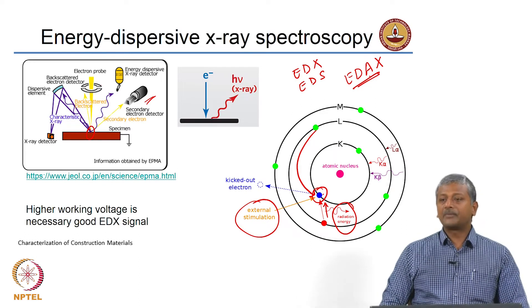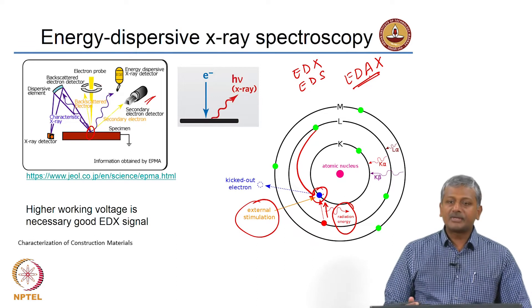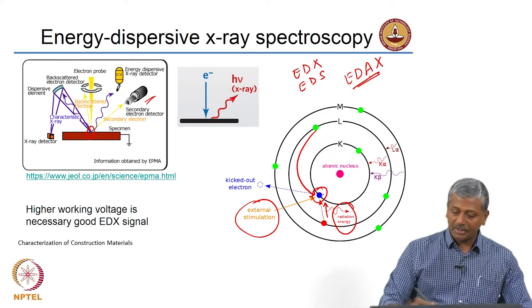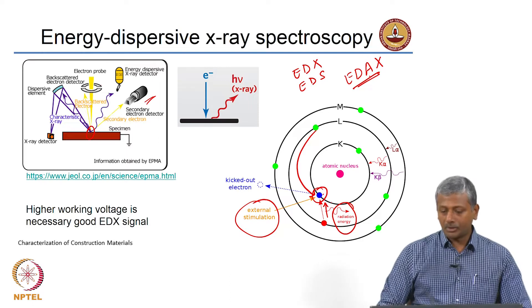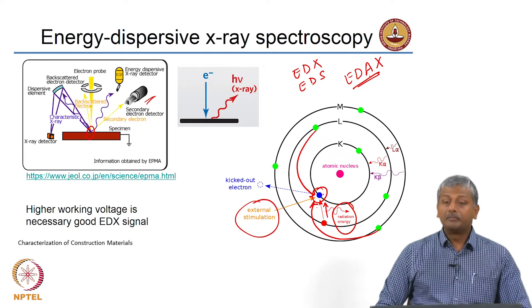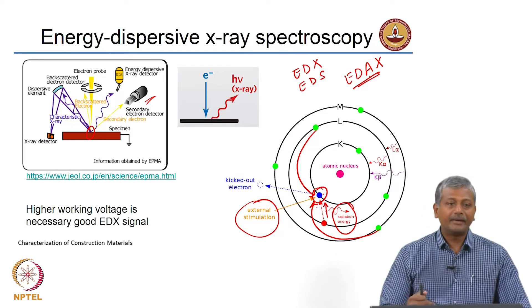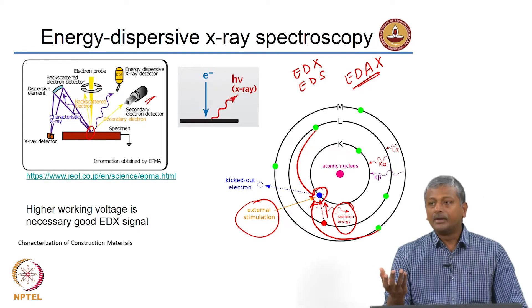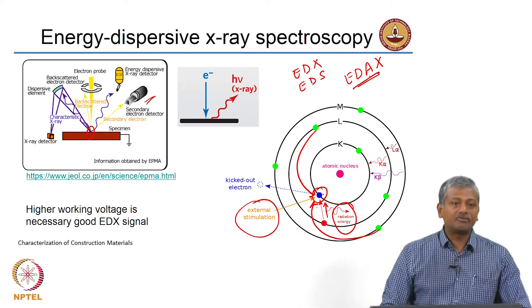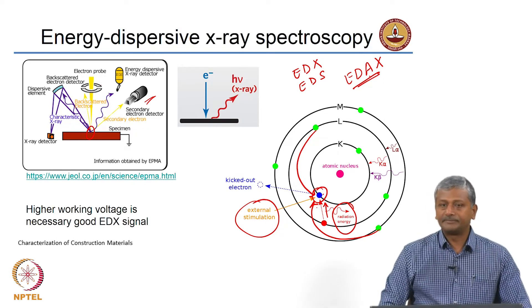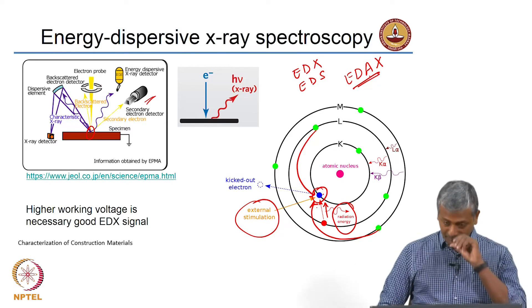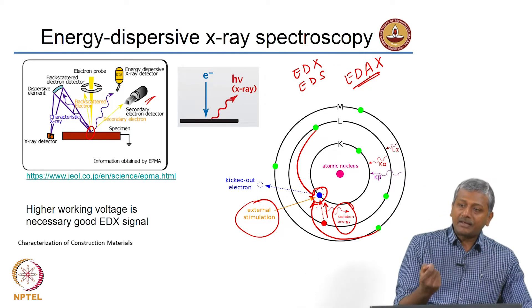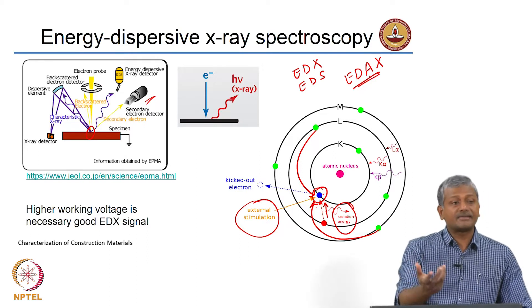When the outer-shell electron jumps in, the energy difference is released as heat and as X-rays. These X-rays are characteristic because they define a very clear energy transition — for example, from the L shell to the K shell (K-alpha), or from M to K (K-beta). The probability of L-to-K transitions is much higher, so you see larger K-alpha intensity and lower K-beta intensity. These are characteristic X-rays generated from the atoms in the sample.